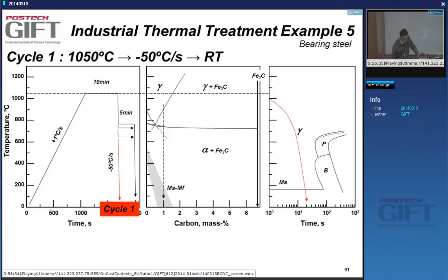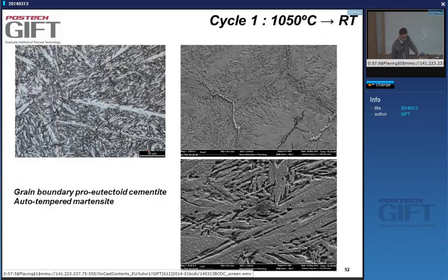So that means you go from this temperature very quickly, we quench. So what do I see? If I can do it fast enough, yes, I should get martensite. All right, let's quench fast enough. Quenching fast enough, 50 degrees per second. It's like you would need to have sprays to get that cooling rate. But it's not very difficult to get this. So this is what you get.